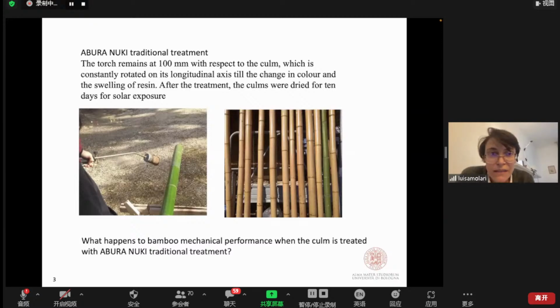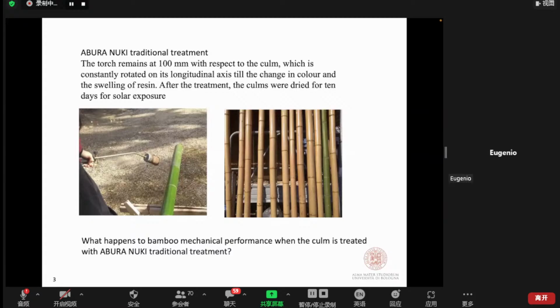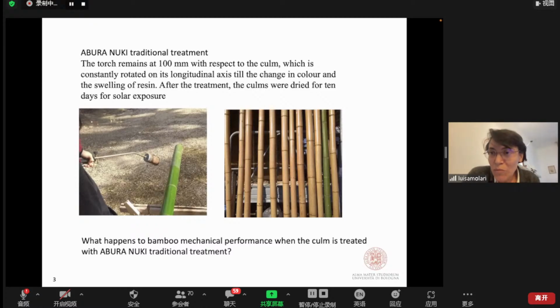This is a Japanese treatment, and it's made with a torch that remains at 10 centimeters of distance with respect to the culm, and the culm is constantly rotated. The torch is moving when there is a change in color and there is a swelling of resin in the culm. After this treatment, usually the culms are dried for 10 days or for some days, usually in the sun. And so our question is, what happens to bamboo mechanical performance when a culm is treated in this way?